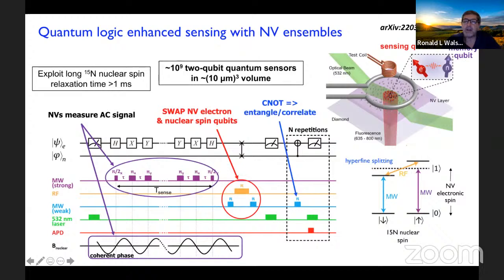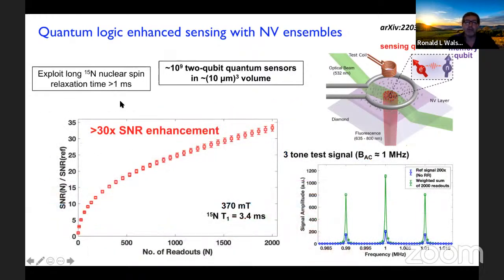We then apply a CNOT to each of the NVs in the ensemble. We do it uniformly to all the NVs. That entangles and essentially correlates the electronic and the nuclear spins. And then we measure the entire ensemble, and we can repeat that measurement many times after re-entangling. So the information is basically read out with the electronic spin. That information is mapped back from the nuclear spin into the electronic spins, and you repeat the measurement. So for every measurement, you get a measurement of the signal of interest, you get many readouts, you get many more photons. The net result is more than a 30x SNR enhancement.